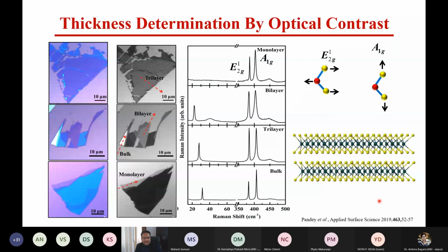So all right, using that we are able to see the monolayer, bilayer, and trilayer. And once you identify the flakes on the substrate, there is another technique called Raman spectroscopy, which shows the thickness dependence shift of the Raman modes, which gives you the idea whether it is a monolayer or bilayer or something. So what you see on the screen here is that there are peaks at 386 and 407